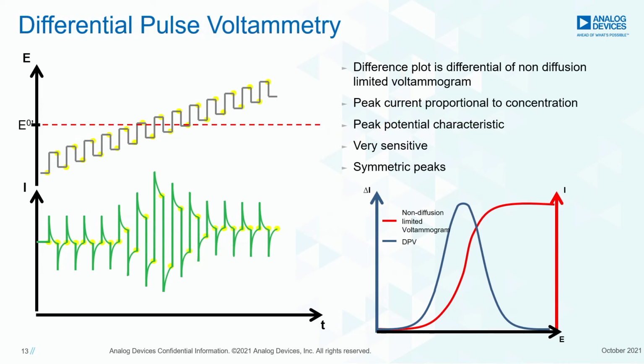It's a great technique. But sometimes you need more sensitivity, and then you look at techniques like differential pulse voltammetry, where you combine a potential sweep, a linear one like you've seen just now, together with pulses. And there the idea is that you jump backwards and forwards to reduce the depletion in front of the electrode. You can imagine when I start continuously to react something at the electrode, it will be depleted. But when we then make a small jump backwards, we produce again what we've depleted a bit, and we give the solution a bit of time with diffusion to bring new species to the electrode.